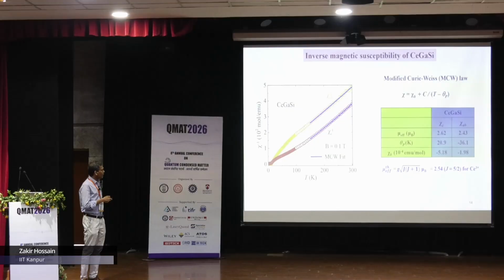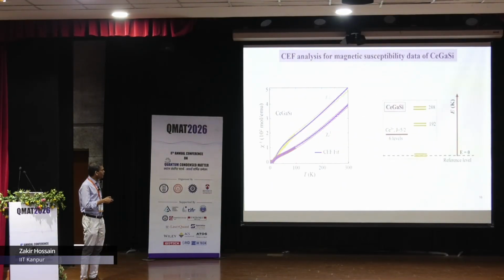So which we have done, and we get this from the magnetic susceptibility. This is our tentative level scheme: the ground state is a doublet, and the second doublet is at about 190 Kelvin, and the third one is about 288, close to room temperature. So cerium has J equal to 5/2. It has only one f electron, it's trivalent, so L equal to 3 and S equal to half. Using Hund's rule, J equals L minus S, that will be 5/2. So 5/2 means the total degeneracy will be 2J plus 1, that will be 6. So one expects 6 levels.